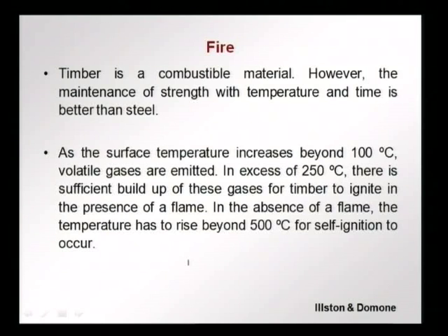However, if there is no flame, there is only heat, then the temperature has to rise beyond 500 degrees Celsius for the wood to catch fire by itself. So, if there is a flame, an active fire, then at 250 degrees Celsius the volatile gases catch fire, but if there is no flame and only the heat is increasing, then the timber itself does not catch fire until about 500 degrees Celsius.